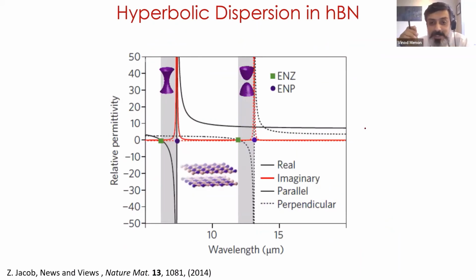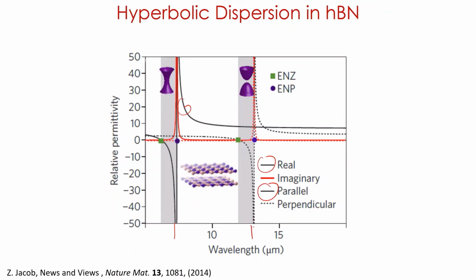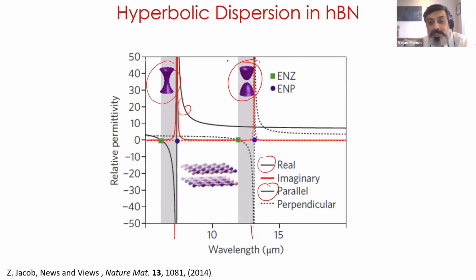So I'm just going to show you what happens in hexagonal boron nitride at these mid-infrared wavelength ranges where there are phonon frequencies. You get this hyperbolic dispersion because you see here the dielectric constant is negative for one. Let's take the real part and parallel part. So the real part is positive and the parallel part is negative. So you get a hyperbolic dispersion in these systems. The same thing happens here. You get the opposite signs at another wavelength range. This is the hyperbola of one surface, hyperbola of two surfaces. So these are naturally hyperbolic metamaterials.